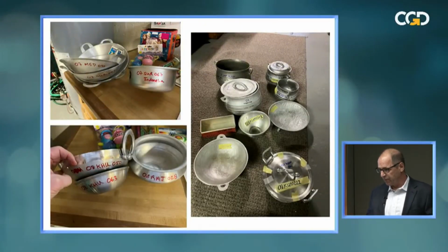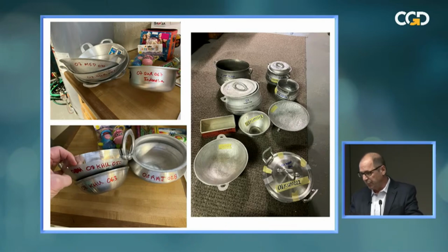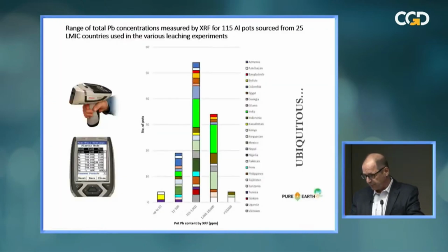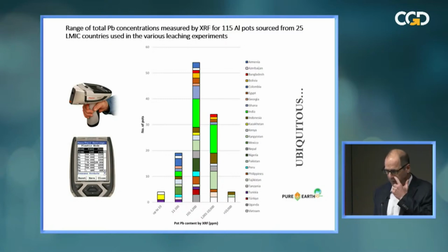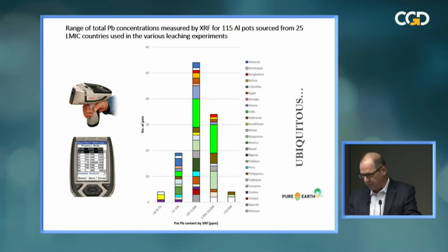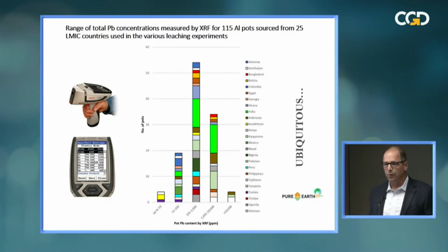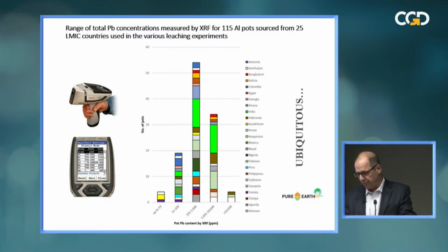What do these pots and pans look like? This is just a brief example of pots from Indonesia, Bangladesh, and Ghana, just to put things in context. We tested all of the cookware items. It was actually 115 for the total study. And again, we found pretty high levels of total lead in the cookware samples. I think the highest was 16,000 in the pots and pans, and over 75% were above 100 parts per million, which you'll hear is a reference level we used in this study. Only 4 of them were above 10,000 parts per million.